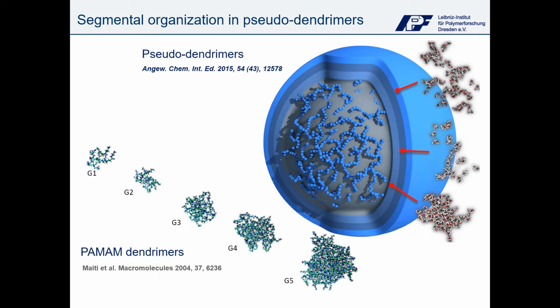the hyperbranched core is getting very compact with every single generation. However, it was interesting to understand how this formation of every single generation is changing the shape of the polymer in comparison to dendrimers, for which we already know very well that with increasing generation number, they still have an open core which can, for example, encapsulate guest molecules.